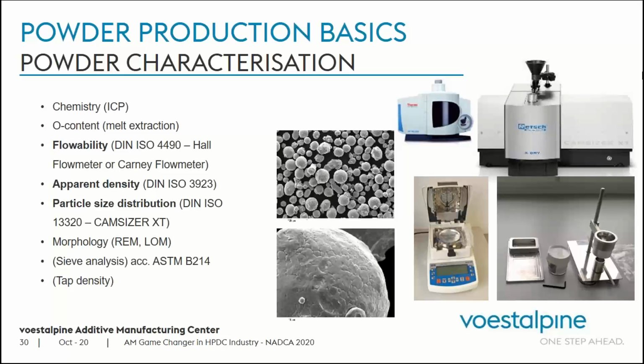So if you look at this, there is multiple testing that has to be done at the mill. Like you have the CAMSIZER, as you can see here on the top right, for the particle size distribution and checking the flowability, and everything is being done according to the standards.